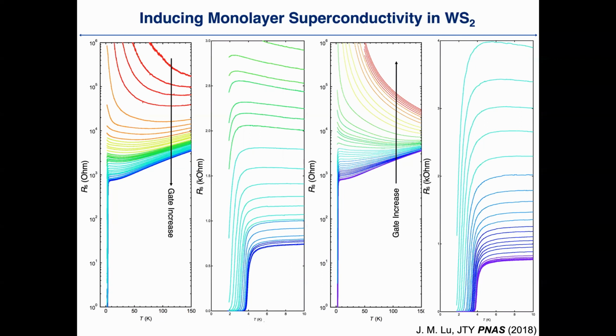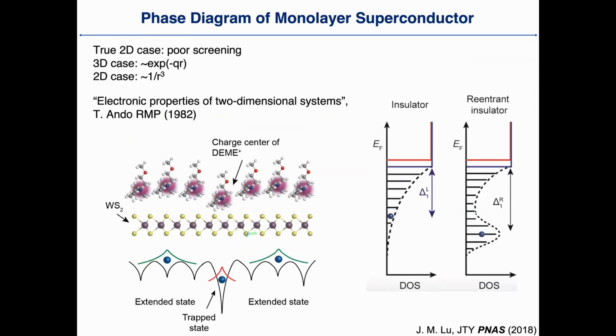So what happened there is like following. If you apply a gate, especially a very strong gate with ionic gating, you are actually limited by the very poor screening of the 2D system. This is not very serious in a multi-layer system, where you have the second layer that is able to screen. But if you only have one layer, in this monolayer case, we have this ion that is very close to the system, and then the field of this ion starts to penetrate and actually forms the trap state.